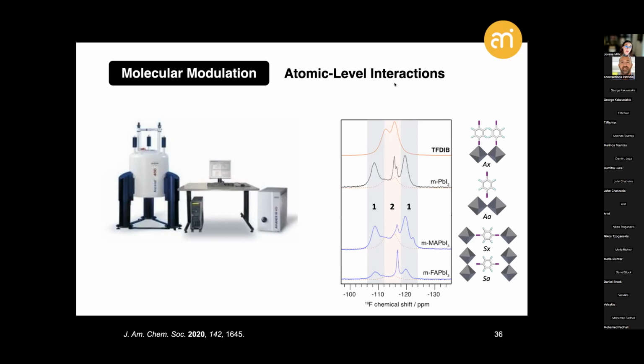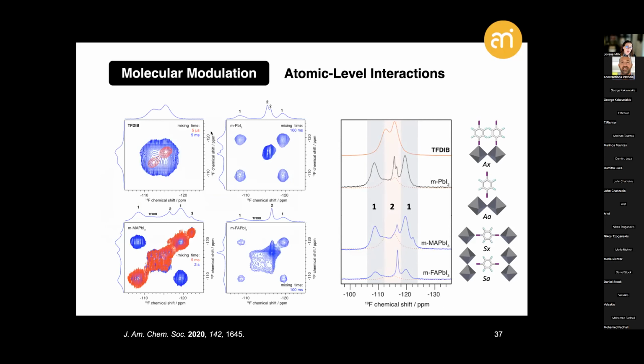Now, to scrutinize these assignments and gain more confidence in their existence, we complement this one-dimensional fluorine NMR spectroscopy with two-dimensional NMR techniques, in this case fluorine-to-fluorine spin diffusion experiments conducted in the group of Professor Lyndon Emsley, that essentially involve monitoring the exchange of magnetization through space, through dipole-dipole interactions between the inequivalent fluorine nuclei. These result in the appearance of off-diagonal signals correlating chemical environments on the corresponding axes, in this case present for species 1, unlike species 2, where such correlations do not exist, suggesting that indeed species 1 can be ascribed to the asymmetric binding mode, while species 2 corresponds to the symmetric binding mode.